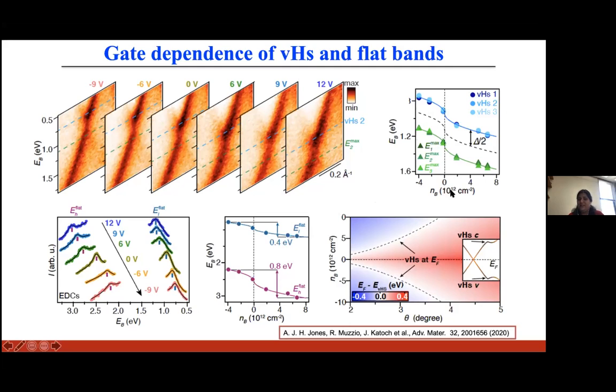by plotting them as a function of the charge carriers in the bottom graphene layer. And so here I'm showing it for all the three Van Hove singularities, and what we observe is that they have a square root n dependence, and the mini gap basically remains constant.